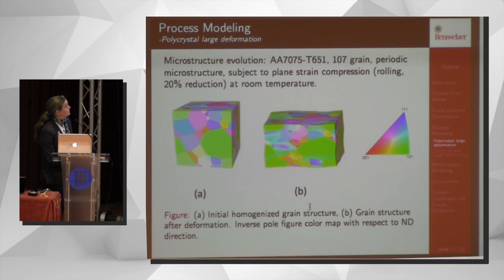For microstructure evolution, here we're looking at aluminum alloy 7075, T651. This is a model with 107 grains as a periodic microstructure. And we subjected it to plane strain compression to simulate rolling to a 20% reduction at room temperature. So we have the initial homogenized grain structure, and then on the right, we see the grain structure after deformation. Now the colors here are associated with the orientations. I have our legend there.